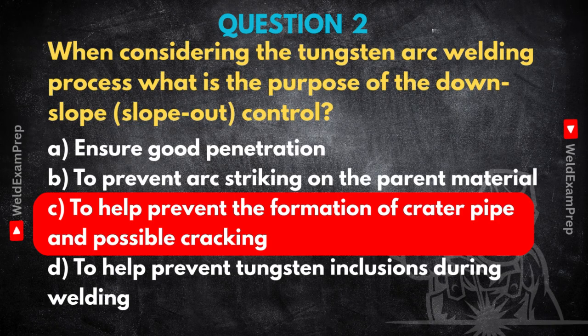Now, if you just suddenly cut the arc, stop dead, that molten pool solidifies incredibly fast, like bang. Snap cool. And that rapid cooling, that shrinkage, creates a little depression or even a void right at the end of the bead. That's what we call a crater pipe.